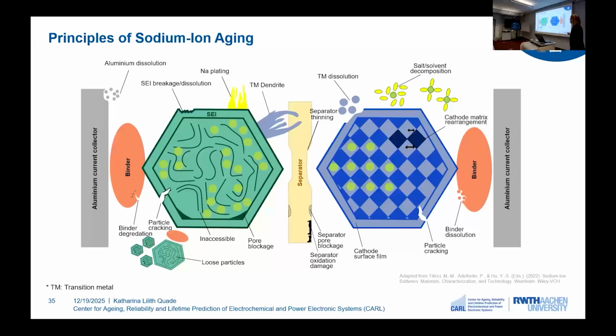On the cathode side, we can see a different set of mechanisms. The cathode can undergo structural transformations that can become, especially at high voltages, irreversible. And we can also see that particle cracking can happen here, again, due to the breathing of our electrode. And again, this also exposes the electrode to further electrolyte and can lead to reactions. We can also see that we have transition metal dissolution, so the transition metal atoms can dissolve into the electrolyte and even move to the anode, as we can see here, and form transition metal dendrites. And these, again, can lead to short circuits. So we can see that aging is highly complex and interconnected.